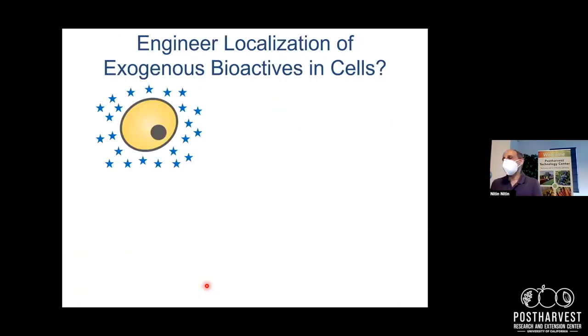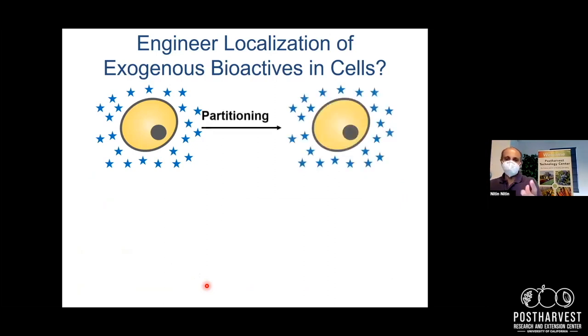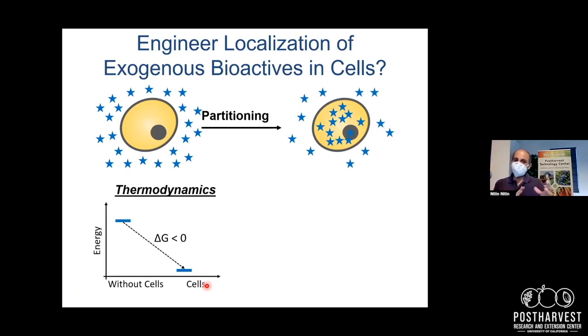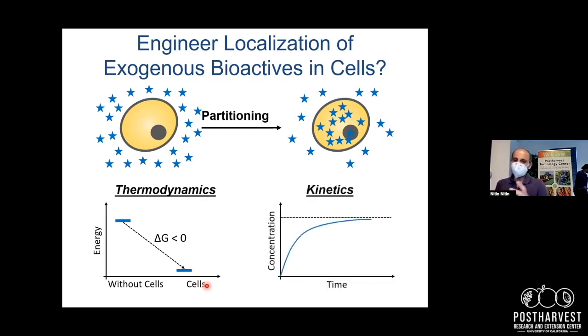In our research program, we have been interested for some time in developing encapsulation systems for controlled release. One of the applications we have been working on is to use yeast as a carrier material for controlled release applications, and I'll illustrate some of them. So we designed a process which allows us to partition compounds into yeast cells. And we can concentrate high concentrations of active ingredients, volatiles, non-volatiles in this environment. Again, the partitioning is designed based on the principles of thermodynamics, which allows the compound to select specific strains of yeast and partition into them. And we can control the kinetics of the process as well as the release in this case.